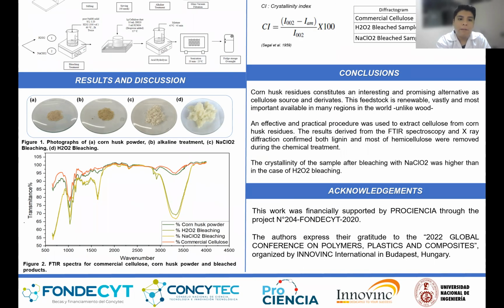Now, about the FTIR, in order to identify characteristic functional groups of spectral bands, we carried out this characterization. Bands of cellulose were found at 1,426, 1,325, and 1,163, while on the other hand, the decrease in signals at 1,251 and 1,736 indicates that hemicellulose and lignin were partially removed after we performed the chemical treatment. The effect was actually more evident in bleaching with sodium chlorite.